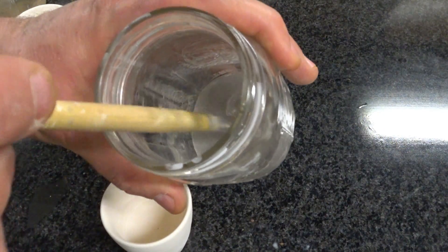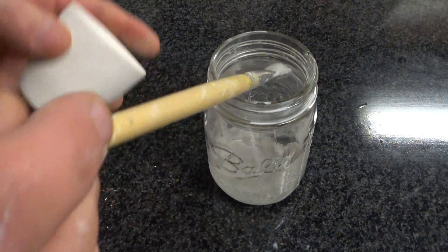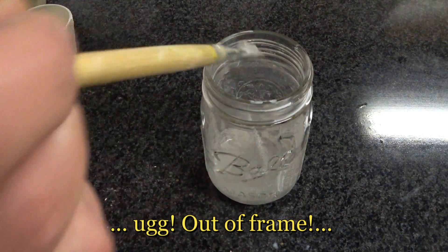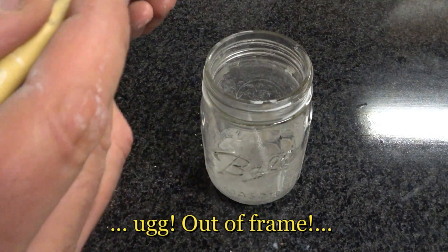Next let's do this one — I have a lot more here, you can see it's a thick sludgy paste. This is rock dust that I picked up at a local quarry when I went to pick up granite slabs for a remodel we were doing. I asked if they had a bunch of slurry I could take, and he grabbed me a plastic bag with the rock dust coming off the saw that was cutting our stones. At the time I hoped we could make a glaze and make tiles for the kitchen from the same stone. I slurried it up and ran it through an 80 mesh sieve, and what we see here is what made it through.